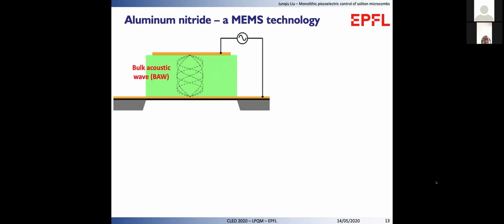As I mentioned very early, aluminum nitride integrated waveguide can also be used for microcomb generation. In the MEMS community, aluminum nitride is one of the most widely used materials to build modulators and filters using bulk acoustic wave. When applying an AC driving on an aluminum nitride thin film, the top and bottom interfaces serve as acoustic mirrors due to the acoustic impedance mismatch between different materials. In this case, an acoustic standing wave can form, which is commonly referred to as bulk acoustic wave.